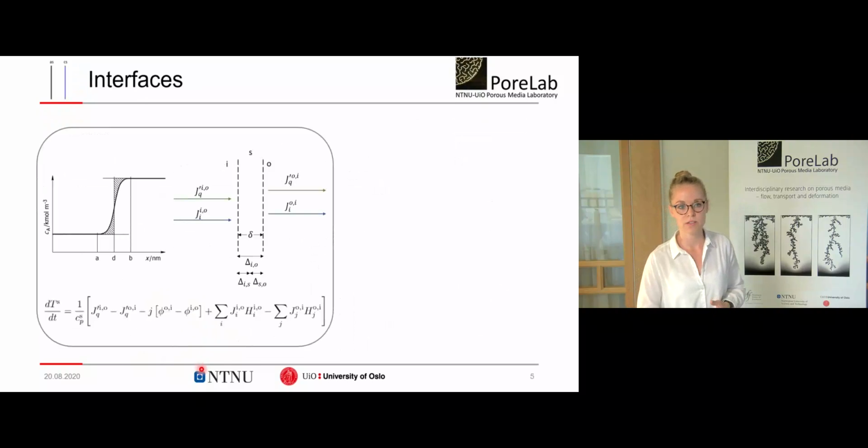So moving on to the interfaces, we define our interface in a way that we have no neutral mass flux over the surface. We also say that all our electrode reactions are happening at the interface, and we treat them as an autonomous thermodynamic system, with fluxes going into the interface and fluxes going out of the interface. And we're balancing around it, obtaining discrete equations for our interfaces, rather than continuous ones as we have for the bulk. So what is already indicated here is that with this discrete treating of those equations, we obtain jumps in our fluxes at the interface.